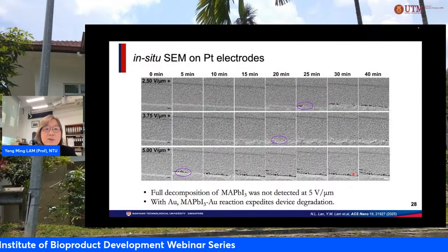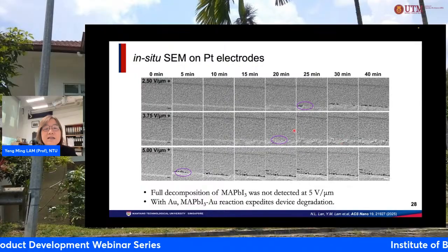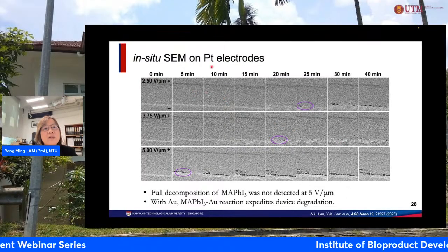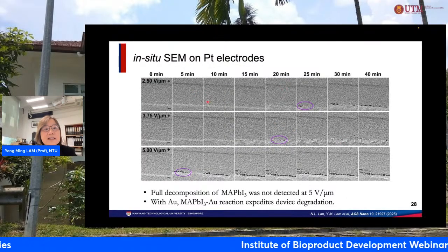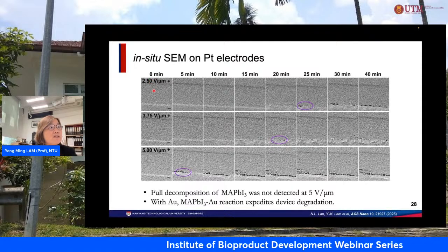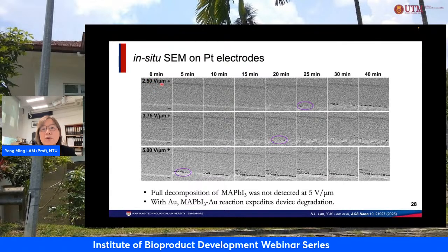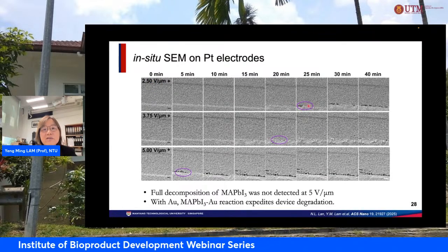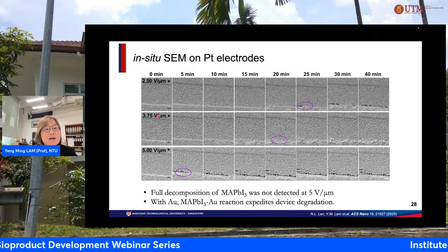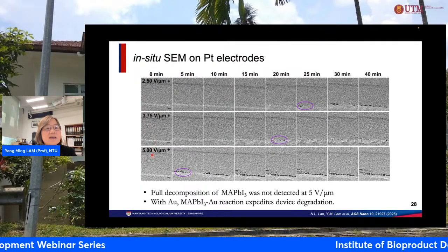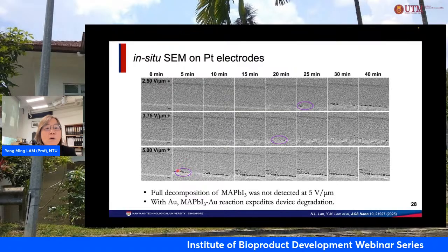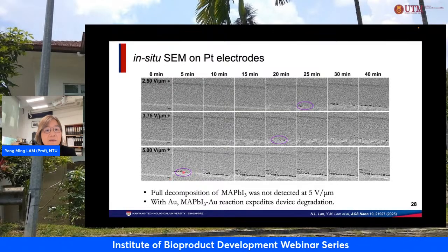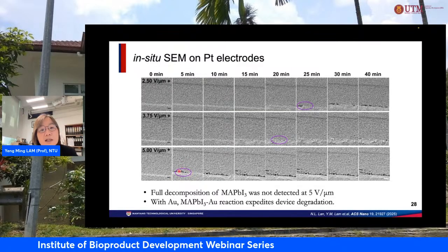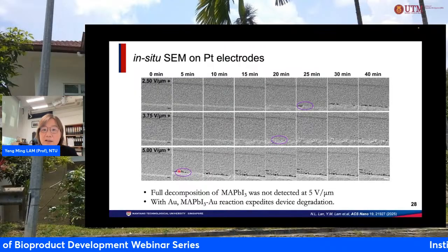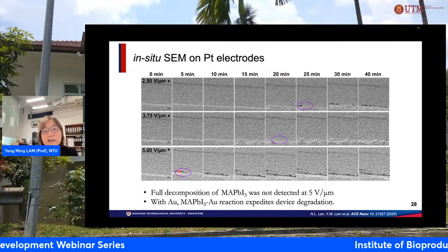So first, I will show you the in situ SEM pictures that we have seen. With the platinum electrodes, we can see that with a very small amount of bias, 2.5 volts per micron, we will see that holes are generated after 25 minutes. But when the bias increases to 5 volts per micron, you will see that the holes generated at the negative electrode happen a lot earlier. So again, it is an indication that it's not stable under high bias.